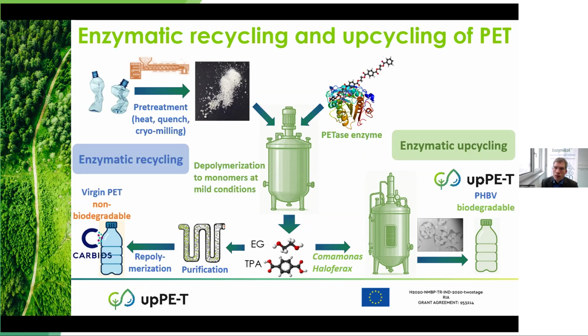And there, pre-treatment techniques such as extrusion and quenching have been developed. Once the PET is amorphized, it can be mixed together with a PET degrading enzyme, the PETase, in a chemical reactor to carry out the depolymerization, very much like in chemical recycling, just under milder conditions. Now we are at a stage where we have the monomers, ethylene glycol and terephthalic acid. And there are now two different options.